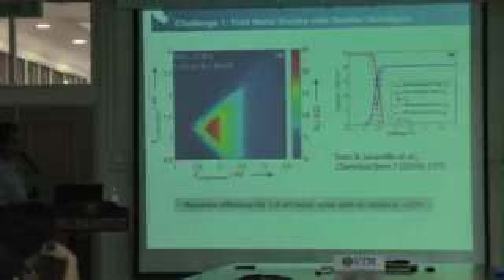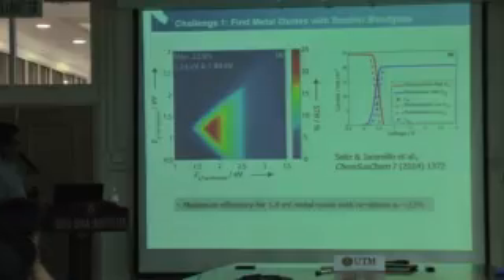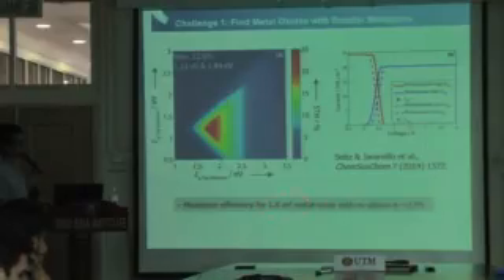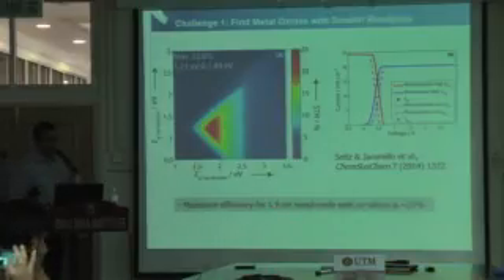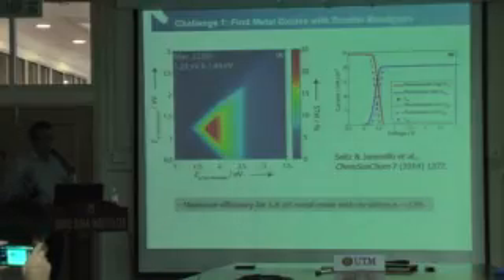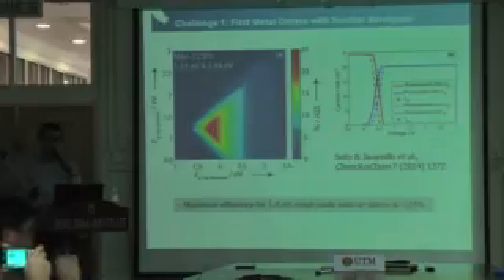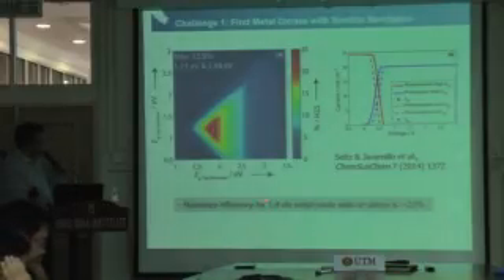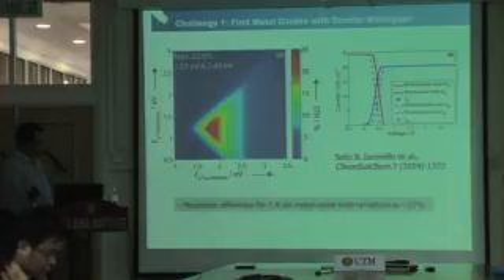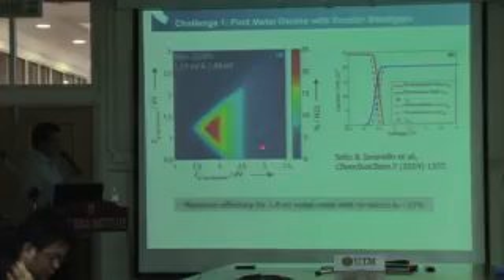So if we try to formulate it more specifically, we want to find a metal oxide, because we like metal oxides, that has a band gap in the range of 1.7 to 1.9, preferably 1.8 electron volts. So that's the direction that we have to go forward. Ideally, with the same kind of carrier transport properties as bismuth vanadate, because we have learned a lot with that material. So if we can get a bismuth vanadate type of material with a band gap of 1.8, we may be able to get more than 20%.